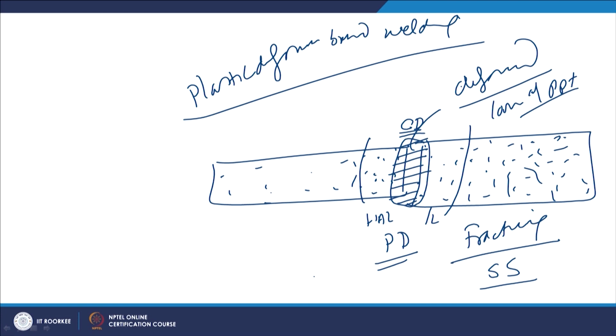If we try to understand this with respect to the hardness variation, then we will see that hardness in the base metal is high, but as we approach the heat affected zone, there will be a gradual loss of hardness, and the minimum hardness will be shown by the weld metal, where the complete dissolution of the precipitates has taken place. On the other hand, a gradual increase in hardness will take place in the heat affected zone, where partial loss of the precipitates is taking place.